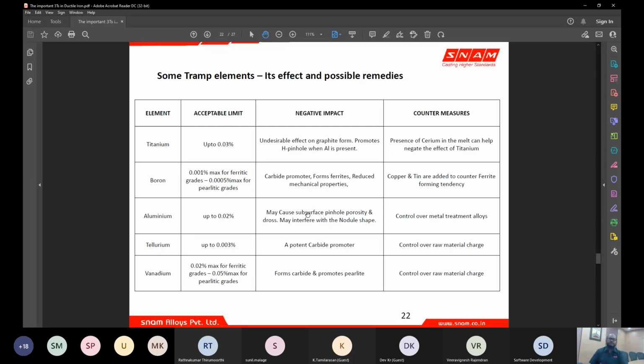Your carbide potency because of tellurium can increase. Slowly this tellurium will keep adding in your liquid metal, which we do not measure, and over a period suddenly you will be getting carbide, and we will be worrying that it could be because of low inoculation, or because of high temperature, but actually there could have been high tellurium present in it.